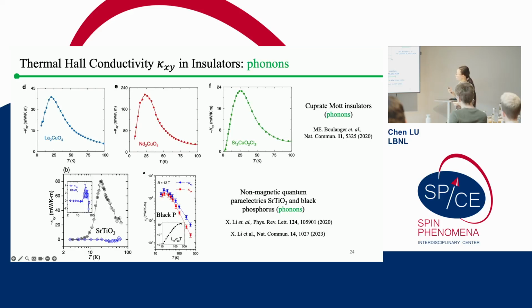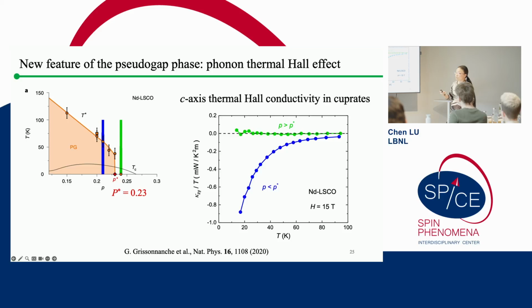Okay, so for the phonon thermal Hall effect, the other very important example is the phonon thermal Hall effect that people detected in cuprate superconductors, in particular related to the so-called pseudogap phase. This is also the result reported by Louis' group in Sherbrooke. So basically what we did is we tried to measure the thermal Hall effect in a cuprate type of material at 2 different doping levels.